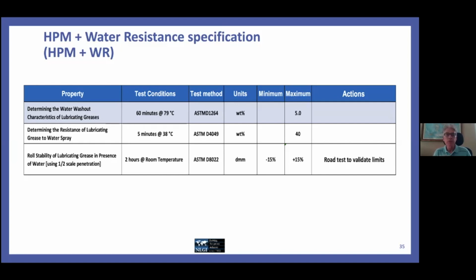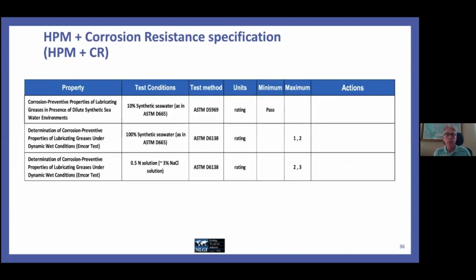And our next specification is HPM plus corrosion resistance. So required to meet the core high performance multi-use grease specification and have enhanced corrosion resistance. And this particular corrosion resistance, though we don't say it in the name or the acronym, the CR, is saltwater corrosion specifically. We already have our distilled water corrosion tests in the HPM core spec. And now we've added 1 static and 2 dynamic tests.